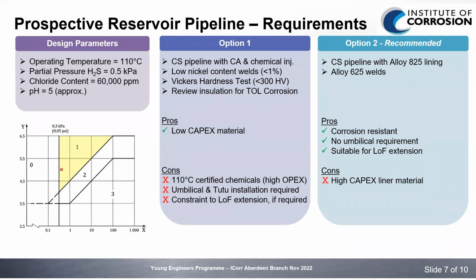Option 2, which is our recommended, is a carbon steel pipeline with an Alloy 825 liner. Commonly used with Alloy 825 is Alloy 625 for welding, so that would be our recommendation. The pros of fabricating the pipeline from this are that it's corrosion resistant. Because you don't require chemical injection, you don't need an umbilical. It would also be suitable for life of field extension, which we see so often these days, which is great long term. The con, of course, is that it's a high capex liner material. However, by going for a liner rather than a full CRA pipeline, we are reducing costs in that area. I'll now pass you on to Mustak, who will talk to you about welding and testing requirements.